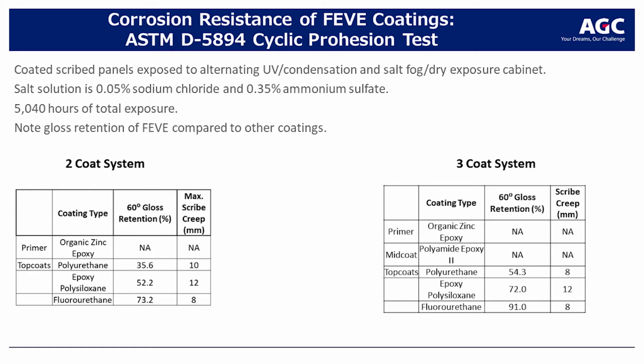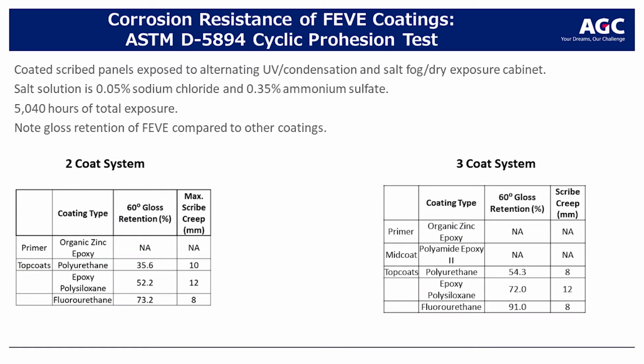You can see in this case they've looked at a 2-coat and a 3-coat system. They looked at organic zinc, urethane, and then a polysiloxane, and then the FEVE or fluoropolymer material. They measured how far the rust penetrated under the scribe. 8 is a pretty good result for that. You'd like to have that as low as possible, but that's not a bad result. You can see in both systems, the FEVE coating is equivalent to or outperforms the other coating products. One thing to notice is they measured gloss retention, and you can see the comparison between the other 2 coating types and the FEVE coating. The gloss retention is much better in the FEVE coating.